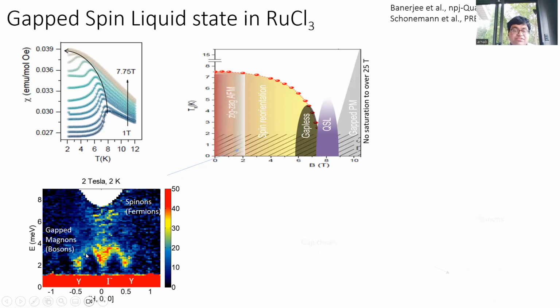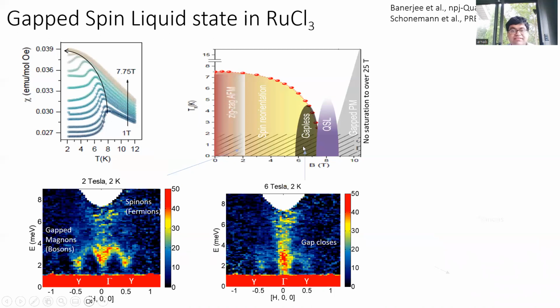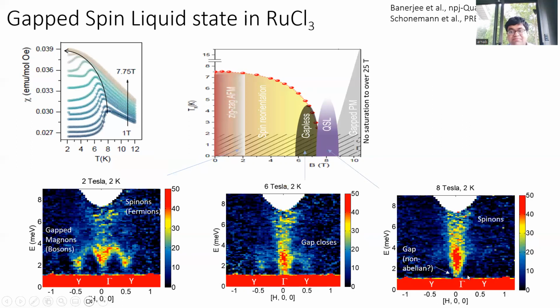We could see that in neutron scattering: we see these gapped magnons with a spinon continuum on top at low temperature and low fields. Then it becomes a gapless continuum. So the gap closes roughly at 6 Tesla, and then the gap starts to reopen at 8 Tesla. So those were the nice features that we see.